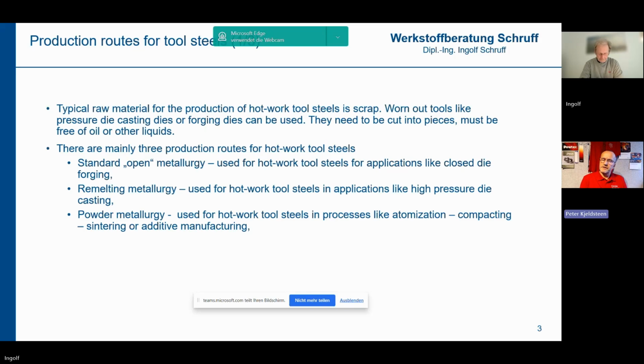Many tool steels are quite highly alloyed, and they form carbides. Some of them form carbides called primary carbides, so they solidify as a part of the solidification curve. Some of the carbides are secondary, so they do not appear until later as a segregation in solid state. When are they formed, and how are they controlled in these 2 processes? They usually appear during or after the hot forming, during cooling from forming or rolling, and during the annealing processes which follow the shaping operations.